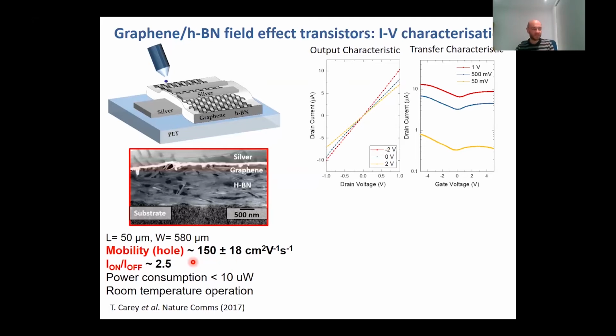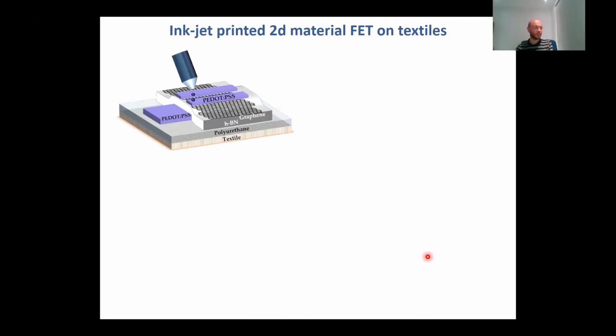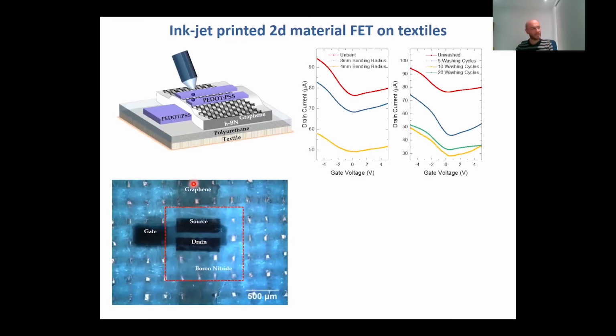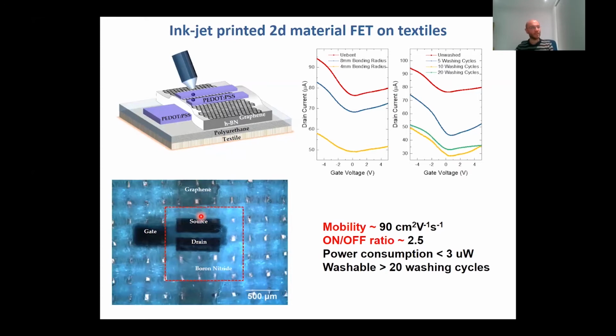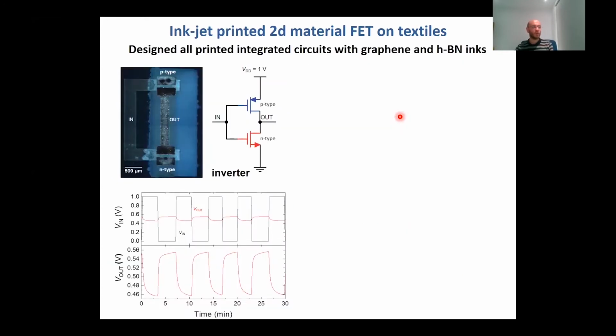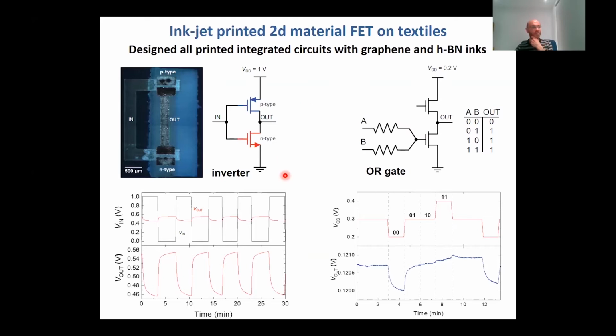The problem, the sticky point, as I said, is the fact that the mobility is very low. So even if we try to make flexible devices, we really need to look for new materials. Of course, we can also make these transistors on textiles. This shows, for example, washability for these devices. But of course, we need to go beyond standard devices made with graphene, which are limited in terms of mobility and also in terms of the output devices that you can get. Here you can see, for example, an OR gate that is following the two inputs, A and B, and the output is giving the OR gate truth table. However, the device is very slow, and this is also due to the very poor on-off ratio of the device.